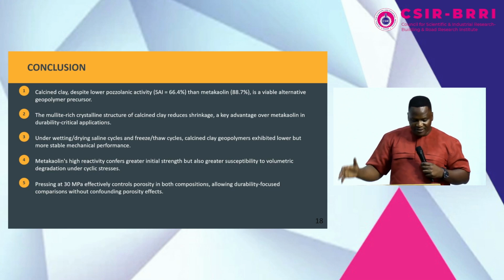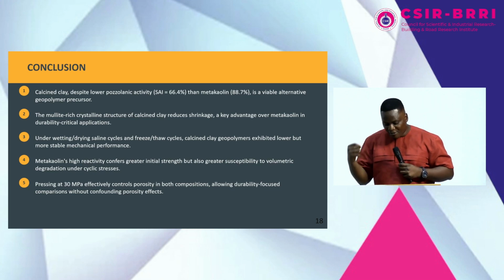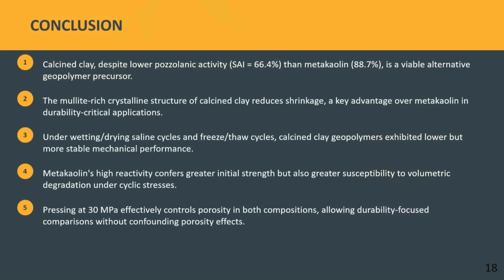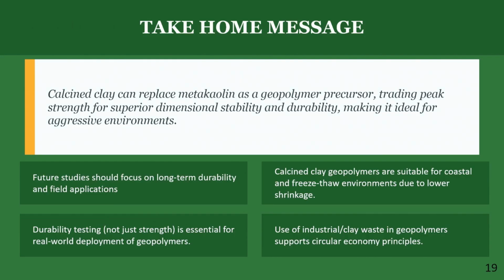That gave it more stability over the metakaolin. Now, metakaolin's high reactivity confers greater initial strength, but also greater susceptibility to volumetric degradation under cyclic stresses. And lastly, pressing the material under the 30 megapascal load was able to effectively control porosity in both of the materials, which allowed durability to be focused on both materials without any one of them suffering any losses. All right, so this is the take-home message.